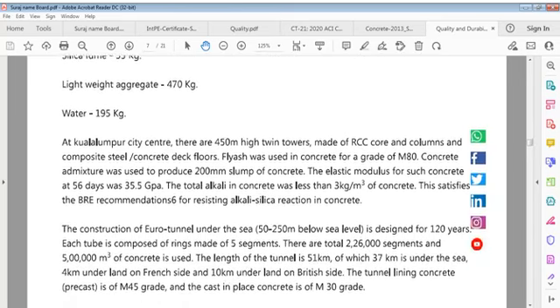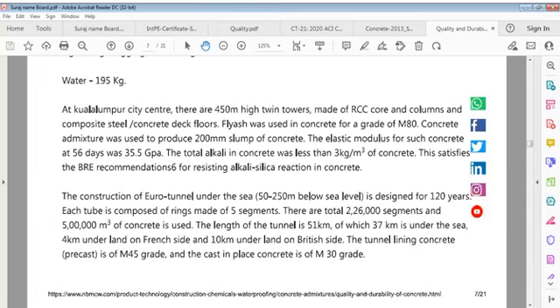At Kuala Lumpur city center, there are 450 meter high twin towers made of RCC core and columns and composite steel concrete deck floors. Fly ash was used in concrete. For a high grade of concrete, admixture was used to produce 200 mm slump of concrete. Elastic modulus of such concrete at 56 days was 35.5 GPa. Total alkali in concrete was less than 3 kg per meter cube of concrete. This satisfies BRE recommendations for resisting alkali silica reactions in concrete.